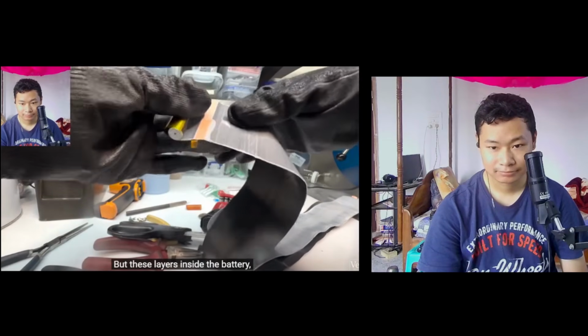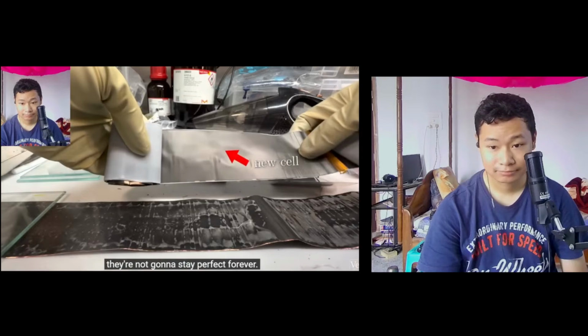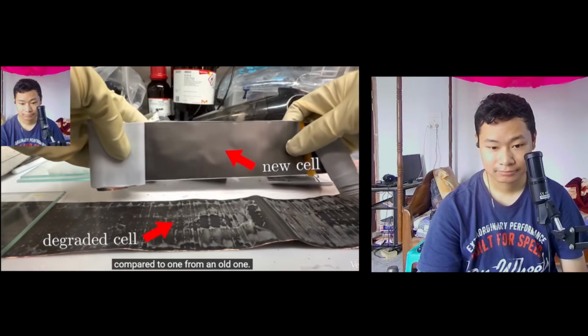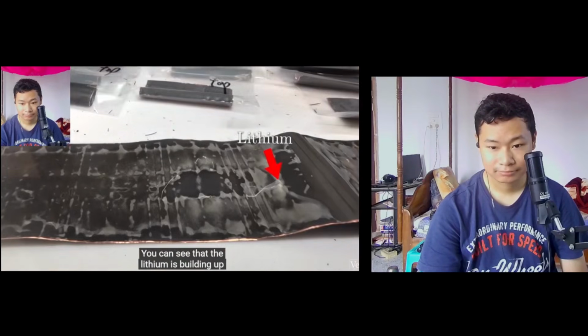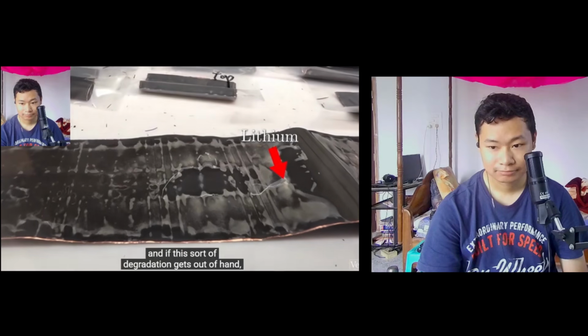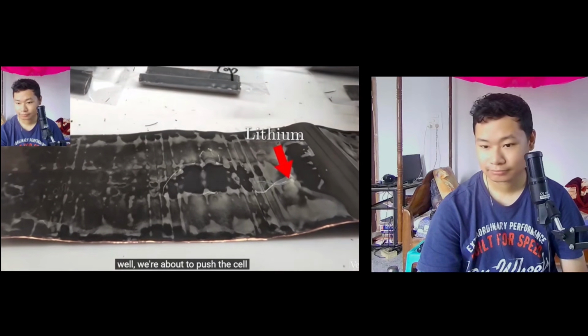But these layers inside the battery, they're not going to stay perfect forever. Here's an electrode from a new cell compared to one from an old one. You can see that the lithium is building up in all the wrong places. And if this sort of degradation gets out of hand, well, we're about to push a cell past its breaking point. How do we blow up a battery?